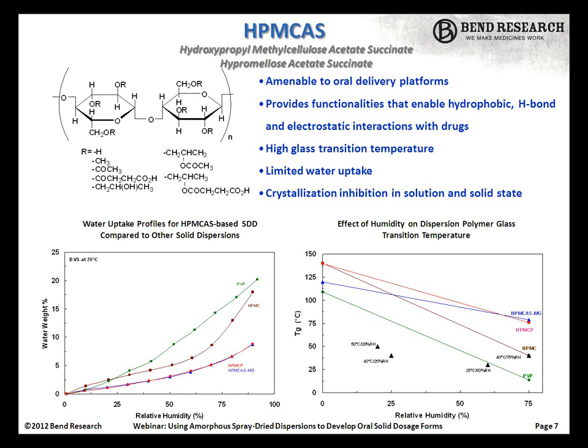The limited water uptake, as you can see on the DVS curves here in the lower left, is limited relative to, say, PVP, for example. That limited water uptake correlates, as you can see on the right here, to a higher glass transition temperature when exposed to water. And the glass transition temperature is a very good first tier indicator for solid state stability. So HPMCAS, as shown in this example, would allow for better physical stability at accelerated conditions listed there, like 40/75, for example.